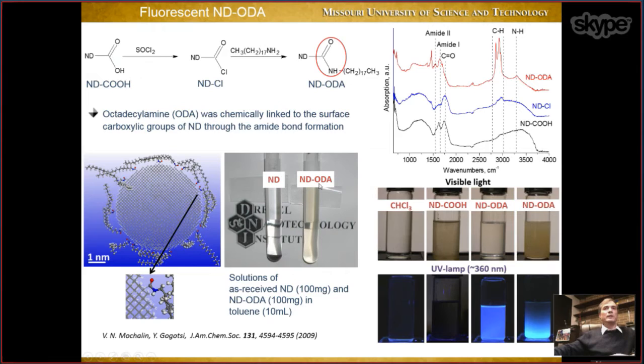So this is ND-ODA, and ODA stands for octadecylamine. So this is this molecule here. So it's very hydrophobic. But this is what we expected when we started this work. What was totally unexpected to us is that this material, in addition, demonstrates very strong fluorescence, which is shown here.